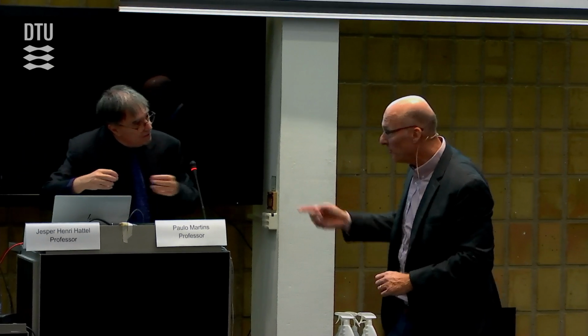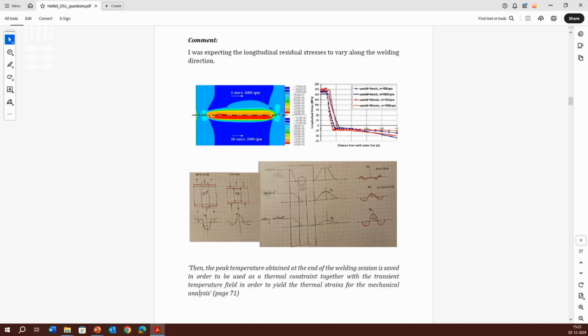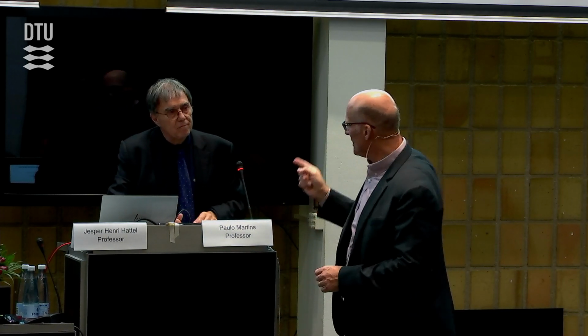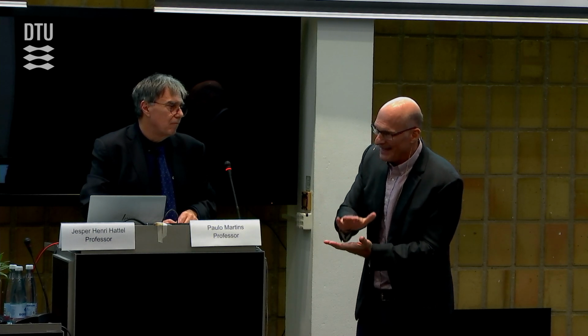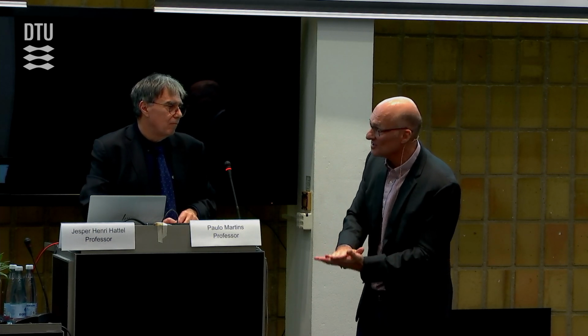Although I would expect to see not a symmetric one, but to see residual stresses. But of course. But this is because this is based on the analytical heat source. And the analytical heat source doesn't take the rotation into account. And this is why it gets symmetrical. But this is what's tricky about friction stir welding, because we also made CFD models. And there we see the flow. And then we did the most advanced model, that was really, really advanced at the time, and actually still is, where the interface condition in a thermomechanical ALE simulation is part of the solution itself.